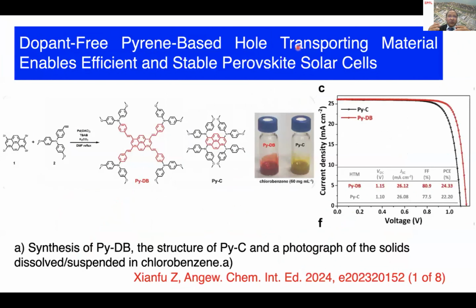So without doping, how do we do that one? The idea is you have to stack the hole transport materials vertically on top of perovskite. To stack the hole transport material vertically on top of perovskite, you need some kind of a planar structure. So here we have taken a planar core, and this planar core stacks. And here, for the first time, without any dopants, as a synthesized molecule, it gives over 24% efficiency.